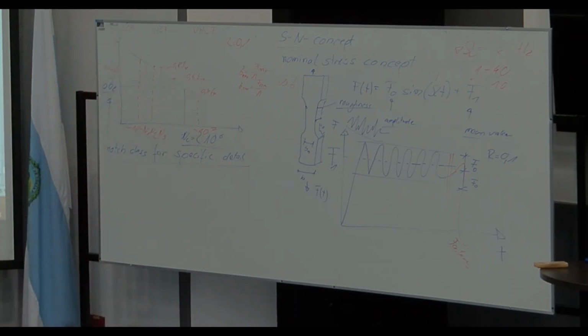So this is our first horizon. The first horizon goes from testing 1 to testing 6, always with a stress amplitude of 240 and a stress range of 480.